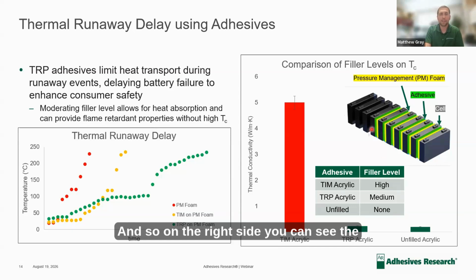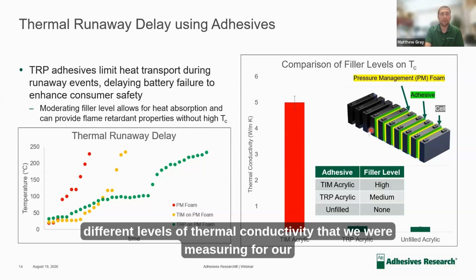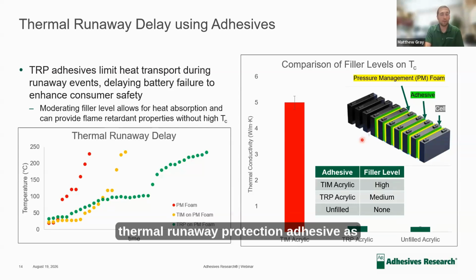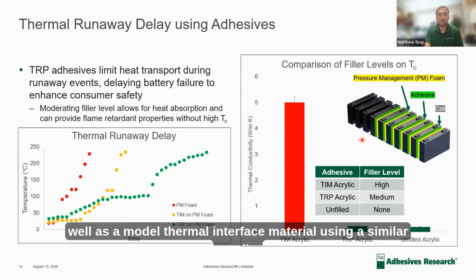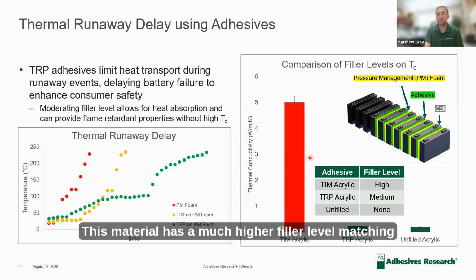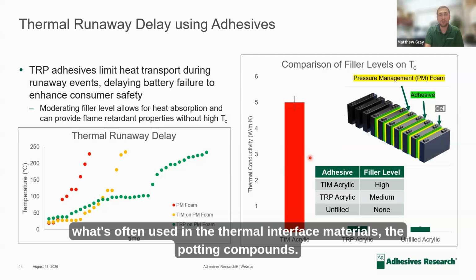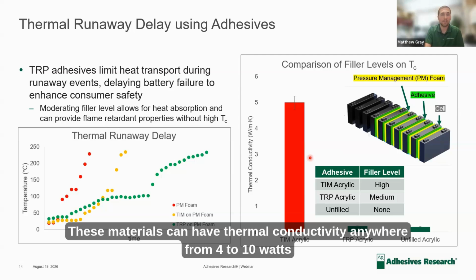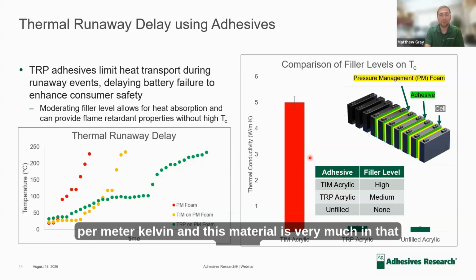And so on the right side, you can see the different levels of thermal conductivity that we were measuring for our thermal runaway protection adhesive, as well as a model thermal interface material using a similar acrylic. This material has a much higher filler level, matching what's often used in the thermal interface materials, the potting compounds. These materials can have thermal conductivities anywhere from 4 to 10 watts per meter Kelvin, and this material is very much in that range.